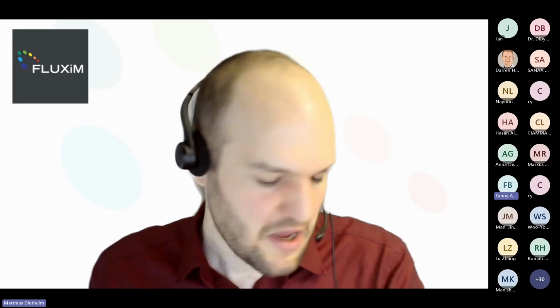So I understand what temperatures are relevant for this experiment, more or less. That's your question. Yeah, as well. I think that we have done experiments at 65 as well. The study that I linked where we looked a little bit at this shunting, we also see it at 65. But in our case, we think that 85 was the maximum temperature that we could use while still adhering to the ISOS protocols. So we're really trying to accelerate the degradation in this case.